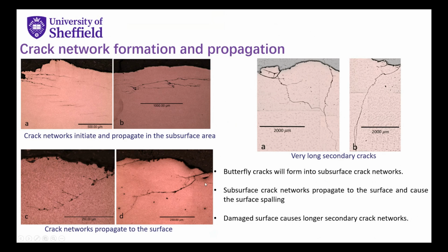And when the surface is already damaged, it will cause very high stress concentration on the surface, and maybe sometimes because the surface is damaged, we may have some impact loading from the rollers. So these kinds of loadings may cause secondary cracks, as shown by the pictures on the right-hand side. These secondary cracks are typically very long because the loading is very high, and it accelerates the failure of the bearings and accelerates the spalling on the surface.